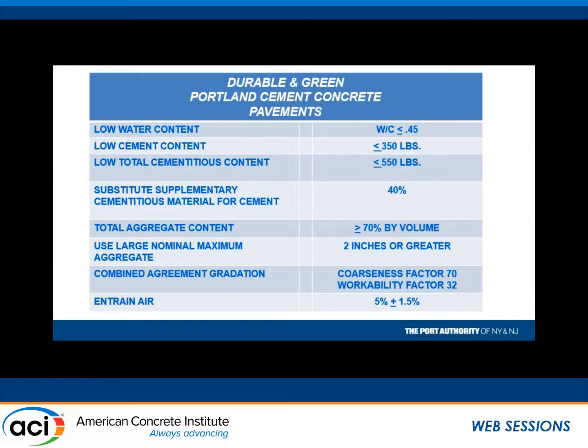Low cement content. The reason why we said maximum cement content, because there's a trend to put in more cementitious material than you need. Okay, for whatever reason, I don't know. It must be very cheap out there. So, we wanted a green concrete. And green concrete doesn't mean that you put in 40% slag and put a hell of a lot of cement in there. Green concrete means you minimize how much cement you have in there. So that's why we put in there maximum 350 pounds of cement, maximum cementitious content 550, which we don't even need, okay, if this thing was done right with the right aggregate gradation. But we cut them a little slack.